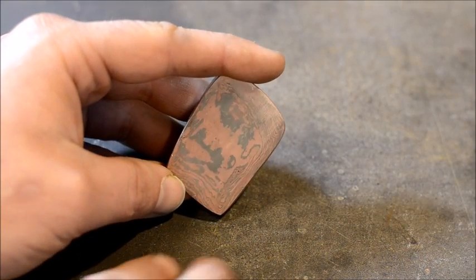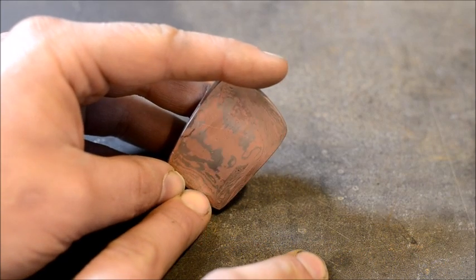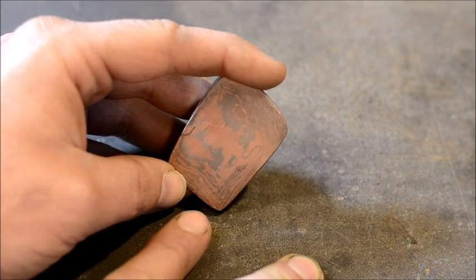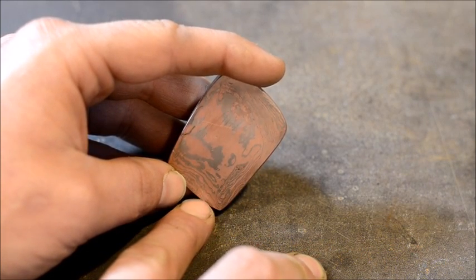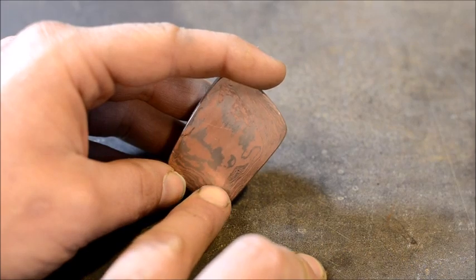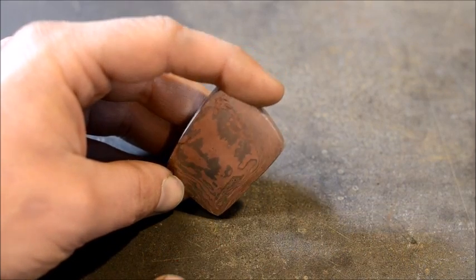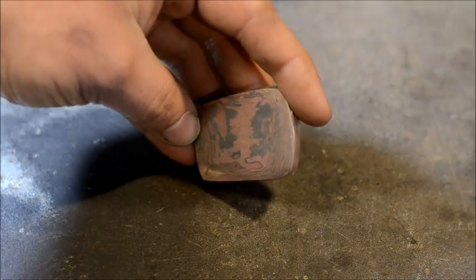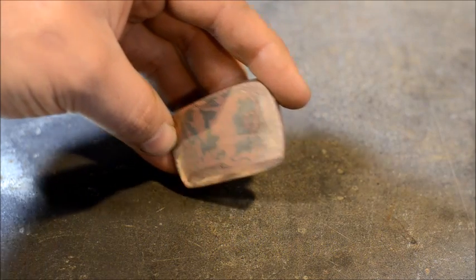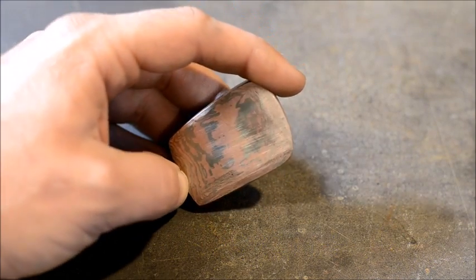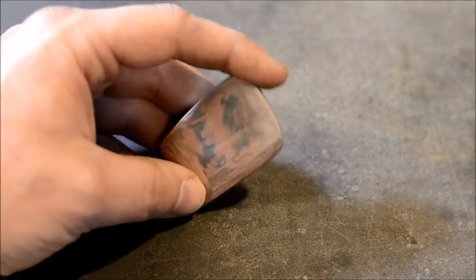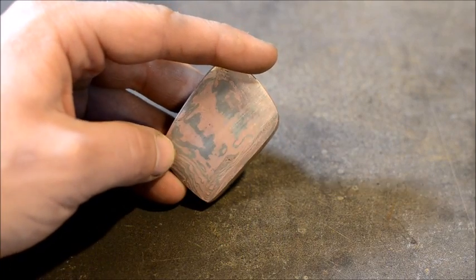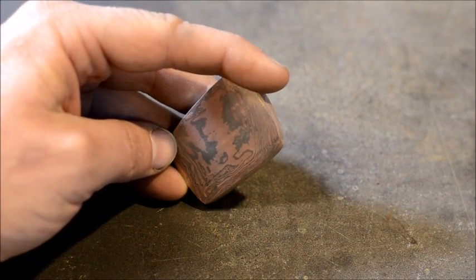What you can see going on here is everywhere you see one of those striations, that was an edge of one of them quarters. As you can see, my stack of quarters slid a little bit on me at a diagonal whenever I was forging this down. So when I sanded this smooth, I revealed those patterns along that edge.